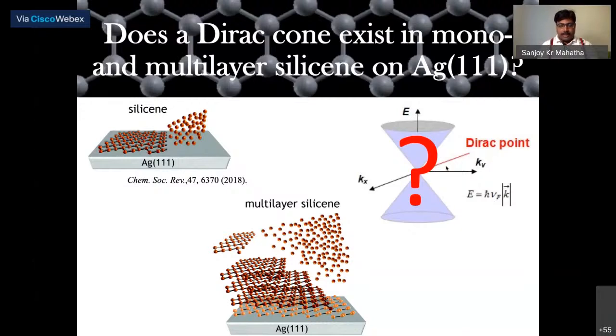And for silicene, so far there has been no report of freestanding silicene. So we have to grow silicene on top of some substrate, and in our case it would be silver 111, on which it doesn't react much. If you put it on other transition metal elemental surfaces, it reacts more than on silver 111.